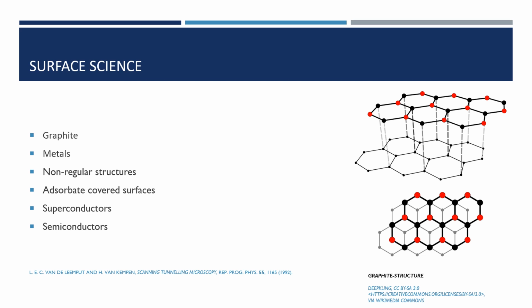Now I will tell you something about the surface science which can be done with an STM. One of the most common and best studied materials with the STM is certainly graphite. Here on the right you can see the graphite structure. Graphite has a layered honeycomb structure. One half of the atoms lies directly above the atoms of the underlying layer, as you can see here in black, and the other half lies exactly in the middle of the honeycomb, in the holes, here in red. Graphite has been studied in many different arrangements by a wide variety of researchers: in ultra-high vacuum, under water, in air, in liquid helium, under oil, and so on.